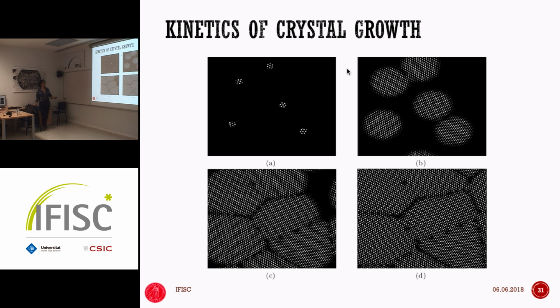For example, this crystallization: you start with seeds with different lattice orientations, and if you start in the phase space where the liquid is metastable, then the crystal is going to grow. You can even have faceted growth and dendrite growth. You can see the snowflakes, but when they are close to each other, they're going to form grain boundaries, and then you get into this polycrystalline coarse graining, and you can study coarsening dynamics and all kinds of stuff.